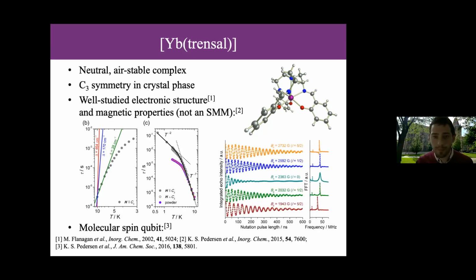Okay, but it's also been studied for its coherence properties, and diluted in the solid state, this is a really, really nice qubit. And so these are different Rabi oscillation experiments on different nuclear spins, so different hyperfine transitions. These should be MI, I think, not I. Different hyperfine transitions of this material. So in the lowest lying Kramers doublet, you can have many different hyperfine states from the naturally abundant nucleus of ytterbium, and you can transfer between these different hyperfine states and perform coherent manipulations. And so these oscillations are proof that you can do coherent quantum manipulations of this material.